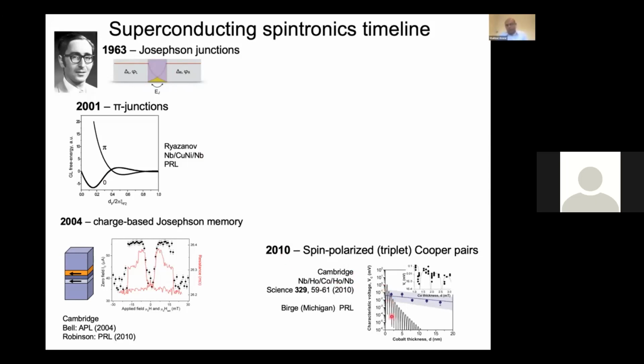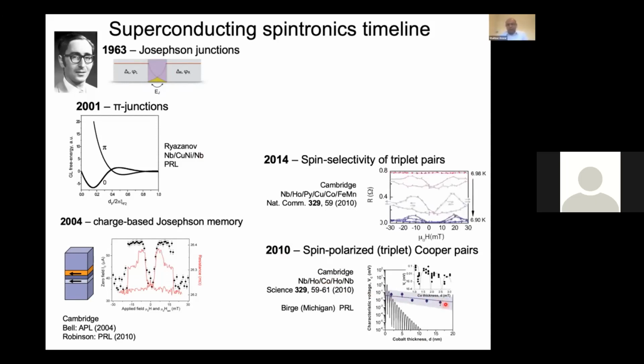this spin polarized superconductor. So here in this figure, you can see that if we are using a single ferromagnetic layer, then the critical current in the device can die off quickly with the increase in the thickness of the ferromagnet. But if we do have multi-layer ferromagnets, then it is not dying off. So it's actually staying even for a thicker total ferromagnetic barrier.